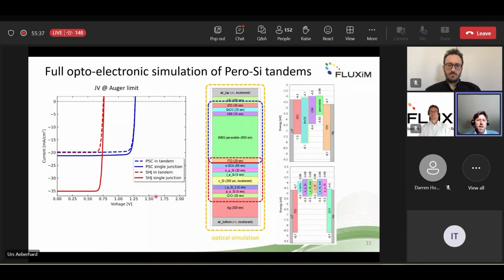Now we start with looking at the situation of the single junction configuration subcells and the filtered subcells in the tandem configuration. This allows you to assess the losses that come from the optical situation. So we have a slightly reduced conserved current here, which is still limited by the bottom cell. So the optics did not change, of course, and we can now compare also the electrical situation in, let's say, isolated condition compared with what happens inside the tandem.